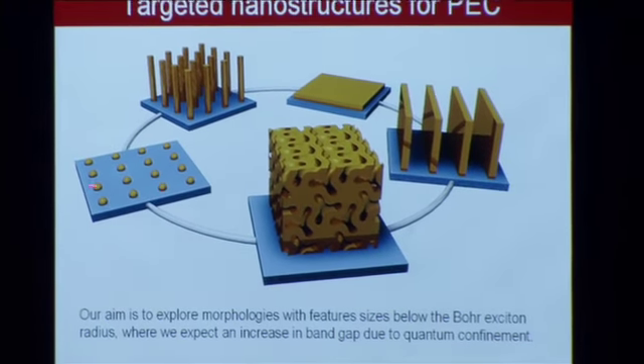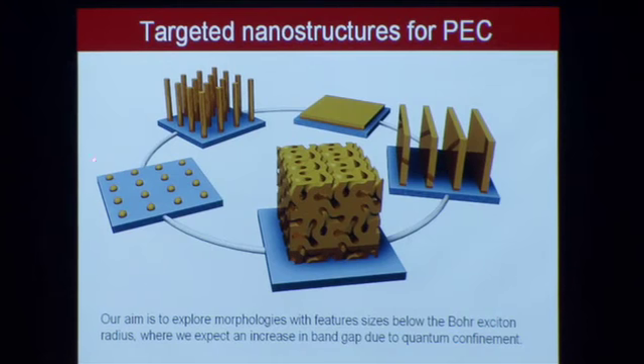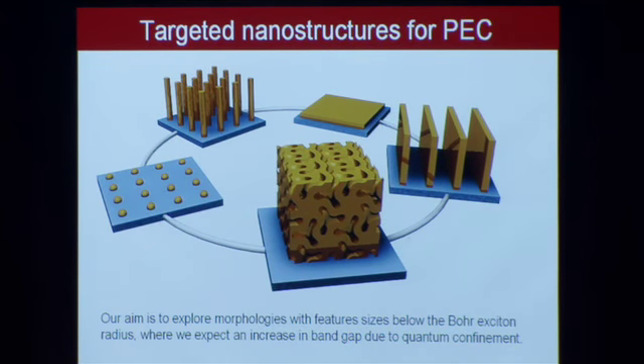But nanoparticles are a good place for us to start. In the end, what we'd like to do is start with nanoparticles that are layered onto a substrate. We don't want them touching. As soon as they start touching, you lose the quantum confinement effect because now the wave functions of the two particles are overlapping at that interface. So we need to keep them discrete from one another, and we need to really keep that size monodispersed. We have to make sure that we don't have a wide disparity in size.